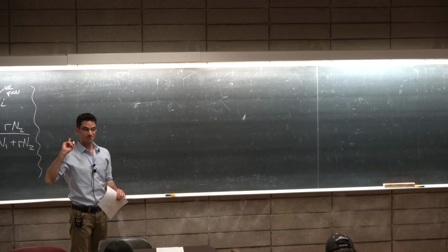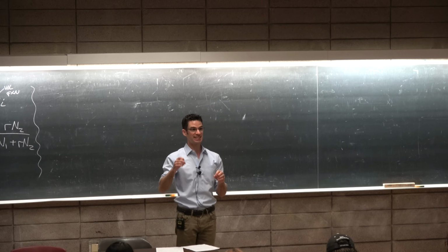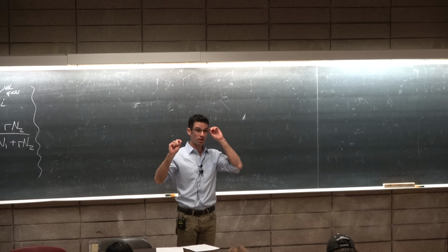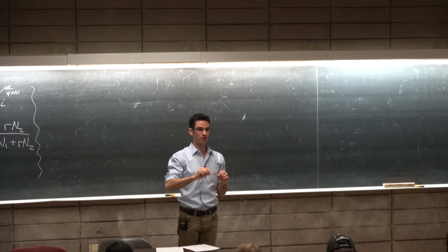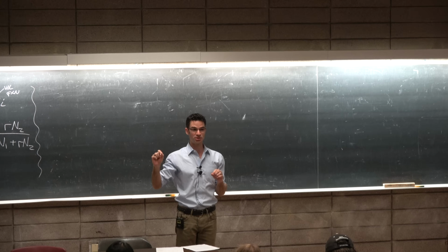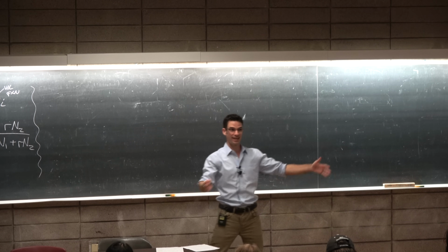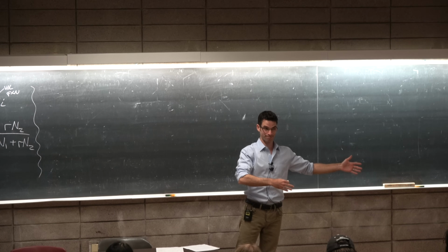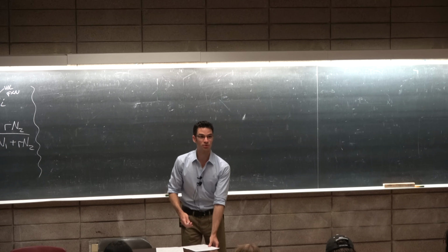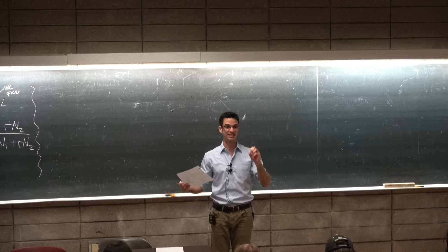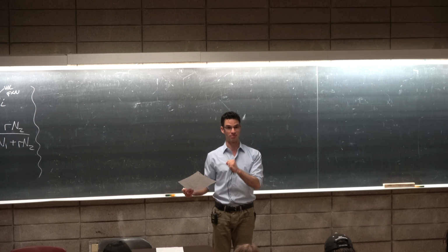As a result, the change in entropy is really just the difference in the number of sites on the lattice where you can put the polymer chain's center of mass, because we're going to assume that the conformational freedom is the same in both the pure phase and the mixed phase. So really all we need to do is calculate the difference in the number of sites available for the center of mass to sit.